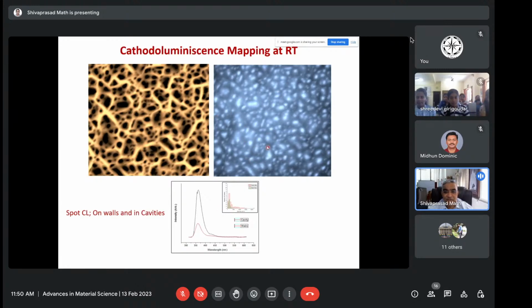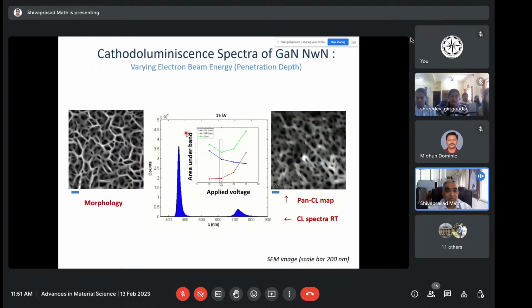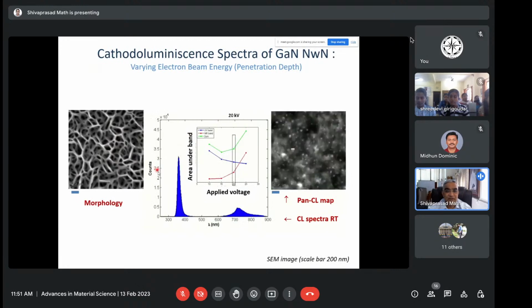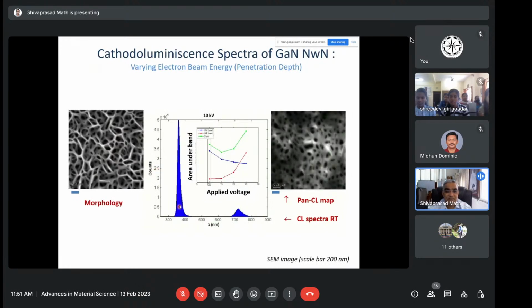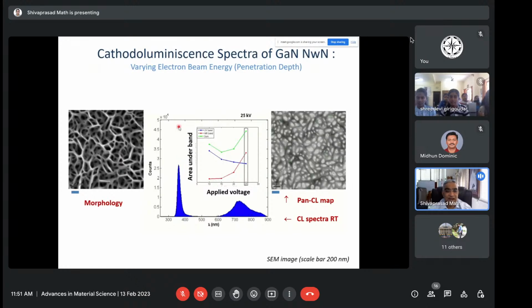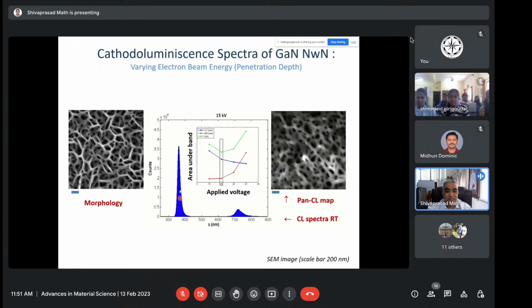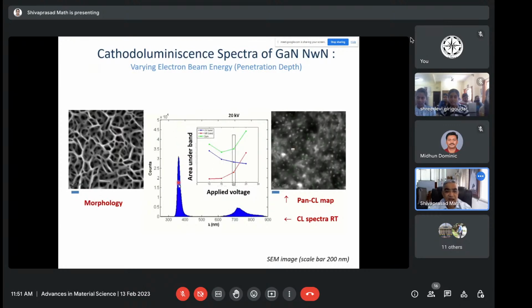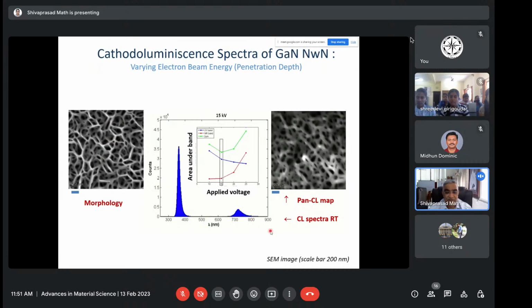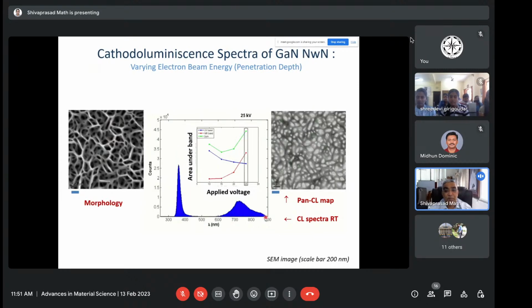And amazingly, what we saw is that the light actually comes from the holes and not from the walls of these materials. Because you see, very interestingly, the wall is the one where the light should come out. But we are seeing the light from these holes, as you can see with the one-to-one correspondence of these signals. So that became very important. Then we started studying it very carefully. When I varied the beam energy, I started seeing something very interesting. One, I saw the bandgap emission, but when I increase the energy of the electron beam, I see the bandgap emission goes down, and another emission at about half the value, or double the value in terms of lambda, goes on increasing. A broad peak starts emerging.